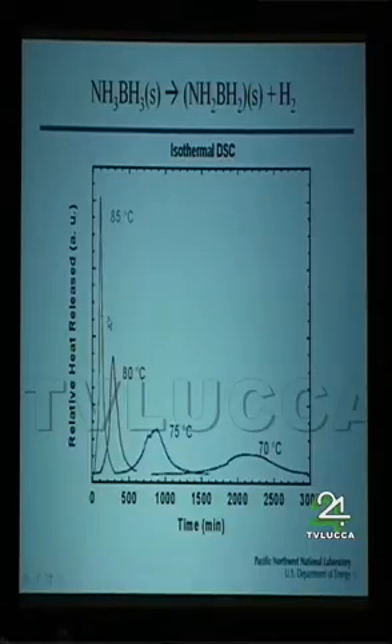And when I first proposed this in front of an internal departmental seminar at the lab, the chemical physics guys showed up, and I said, well, what we want to do is get some sort of estimate of the activation barrier. We're going to assume that half the reaction's over when half the heat's released or half the hydrogen's released, and we have a half-life as a function of temperature and time, and then we can plot Arrhenius and get an activation barrier. And they said, well, that's a little naive.